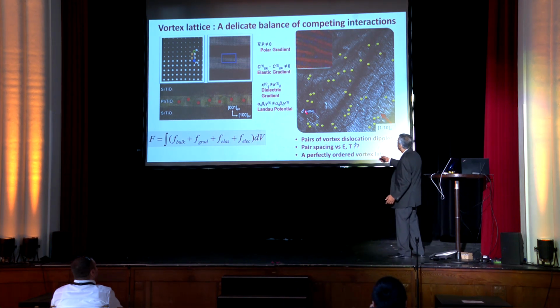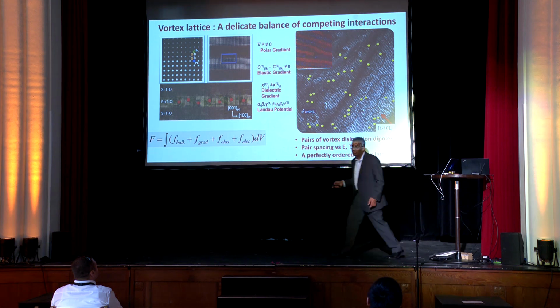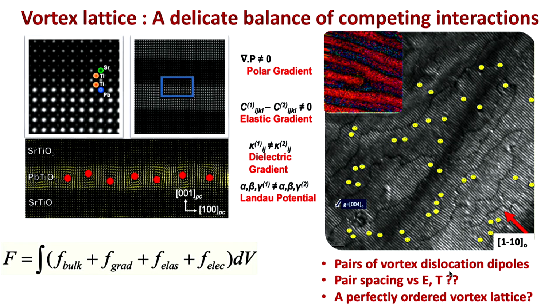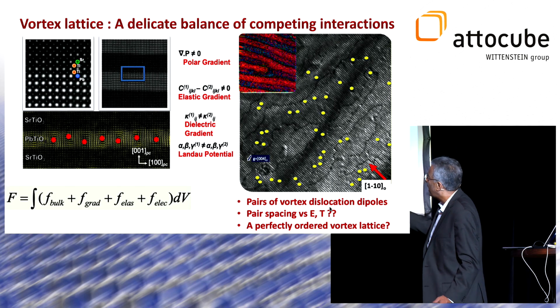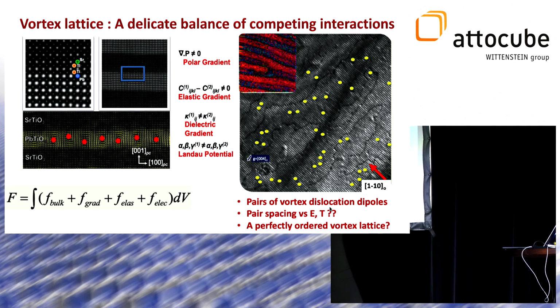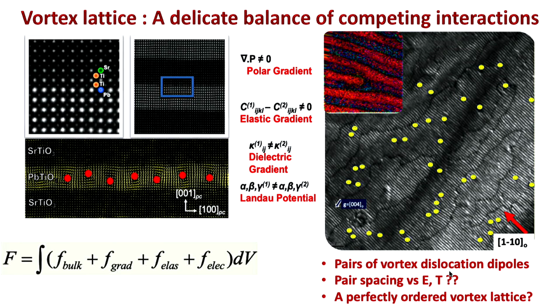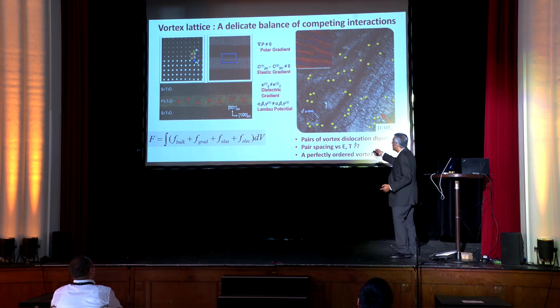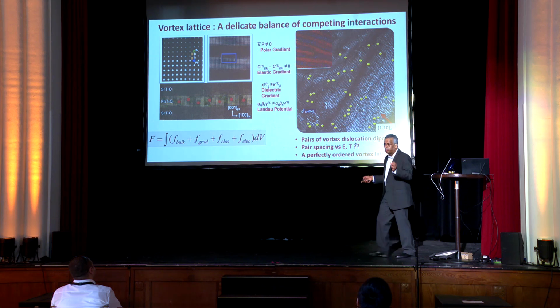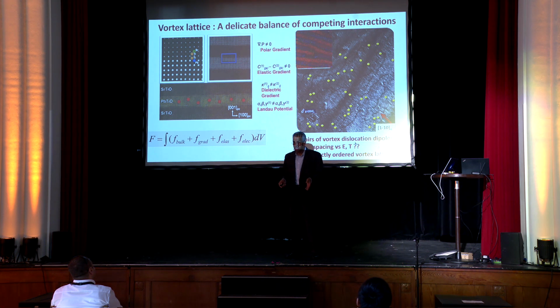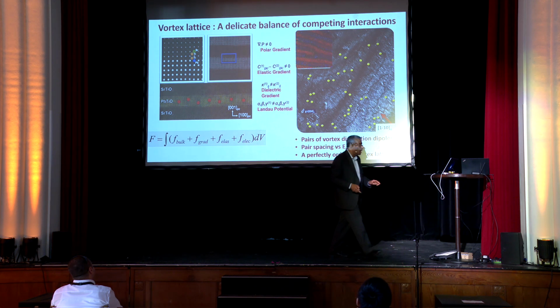Okay? And so you could also see on this picture, these vortices have interesting defects. And this is really going back to the stability, the thermodynamics of 1D and 2D lattices. A lot has been done on this. There has been a fantastic amount of work done in the superconductivity area. But if you look at these smiley faces, I'm not sure if you can see it from the back. These are the smiley faces, but some of them are up, some of them are inverted. They correspond to pairs of dislocations. So if you go back and look at old theories, or even the Kosterlitz-Thouless idea, the whole phase transition is being mediated by the formation of topological defects, like a dislocation. So indeed, you can image those dislocations. So the question is, can we get a perfectly ordered 1D lattice of these vortices, or is it always going to be defective? Nobody knows that. So it's a huge opportunity for research.